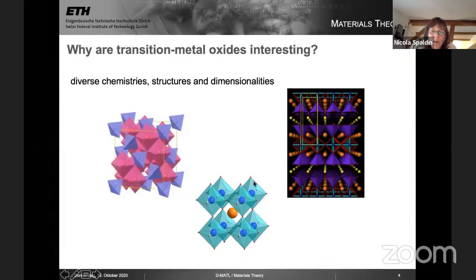And then the structure at the bottom, which is actually the structure I'll probably discuss most today, is the perovskite structure, in which the transition metals, in this case, are octahedrally coordinated by oxygens. So they're in an octahedron of oxygen ions. And these octahedra are shared together at the corners, forming a 3-dimensional network. And then there's another different cation filling the holes in between. So of course, this diversity in the chemistry and the structure and the dimensionality can give us a very wide range of physical properties.